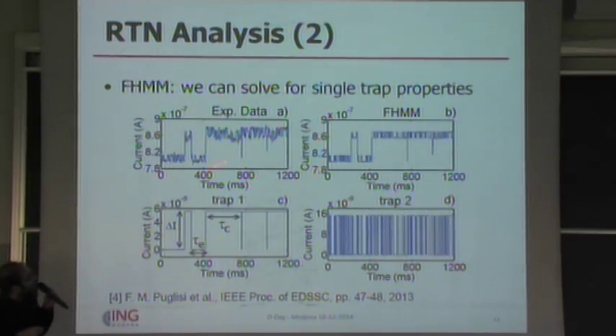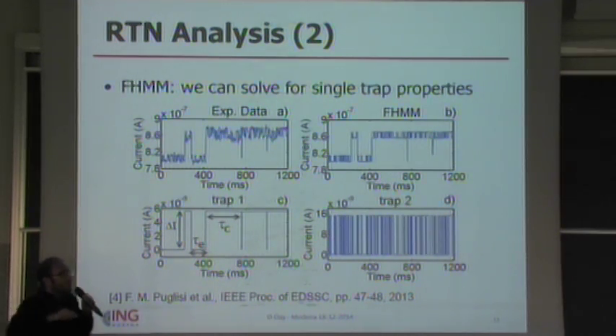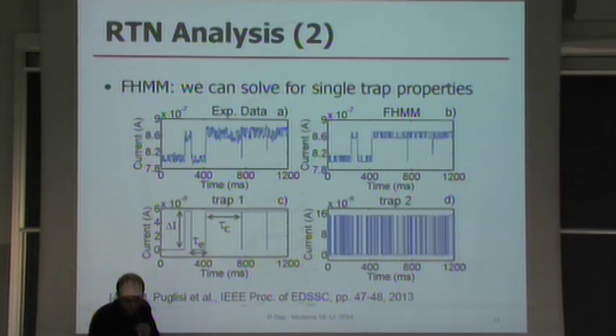We take a multi-level RTN, this is experimental data, this is the FHMM fitting, and with this technique, the technique itself is telling us, okay, you need 2 traps this time, 2 defects. It's the technique telling us that we need 2 defects to properly characterize the signal, and this signal is actually the superposition of this, defect 1, and this, defect 2. So I can characterize the statistical properties, the amplitude of the fluctuation, and the typical time spent by the system in each state separately for the 2 defects. This fluctuation here is actually this tiny fluctuation over here. There are 2 different scales. So we can really perform a multi-defect spectroscopy. We can simultaneously but independently study different defects, and we can know how many defects we need.